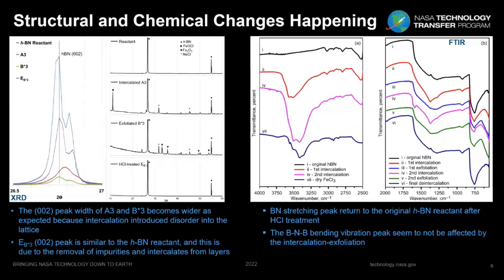So in this chart, I'm showing you the different structural and chemical changes that are happening during the intercalation and exfoliation process. First, I'm showing you the XRD, which shows the structural changes. In the blue line, you can see the original boron nitride without any reaction. It has a sharp 002 peak, and the full spectrum shows a clean spectrum, just the two different boron nitride peaks. When you intercalate, the product A3 in this case, you see that the 002 peak declines considerably. In the full spectrum, some other products like iron oxychloride appear along with the boron nitride peaks.